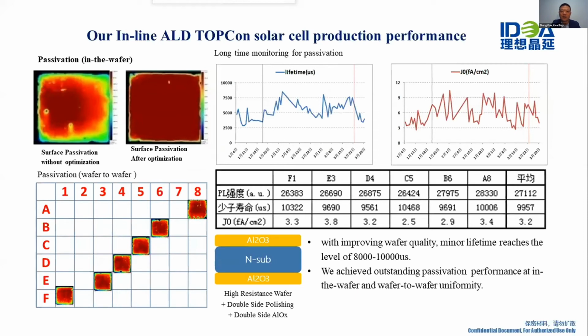And this TOPCon solar cell production performance data has proved the very good quality of our aluminum oxide film. We have achieved a very good minority lifetime, about 10,000 microseconds, and excellent J0 performance, average about 2 to 3, or less than 4. So from this, you can see our aluminum oxide film quality is very good. And this makes a very high solar cell efficiency for customers.